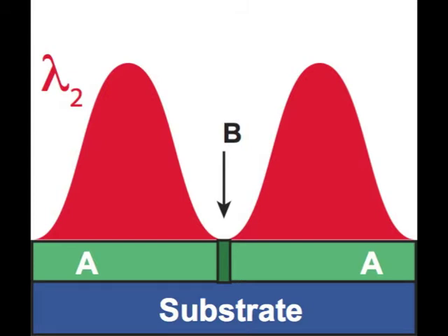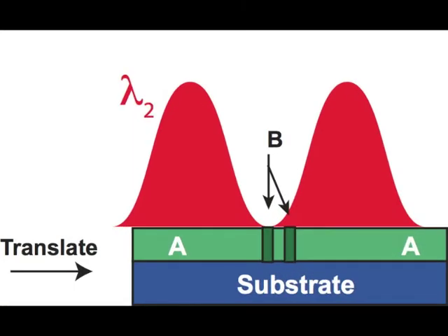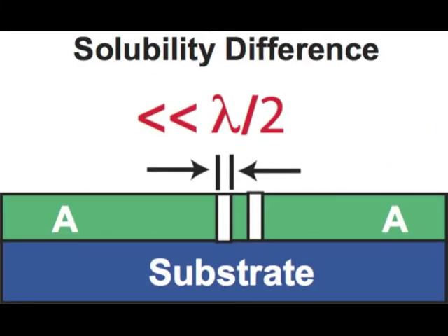Since the beams affecting the saturable transition are inevitably diffraction limited, the breaking of the diffraction barrier is a result of the saturation that is left out at the zero intensity node. Translating the sample, the process can be repeated to create complex geometries in a dot matrix fashion. Finally, due to the solubility rate difference, state A and state B can be selectively removed in a polar solvent, leaving behind subwavelength features that can later serve as a resist for pattern transfer into the underlying substrate.